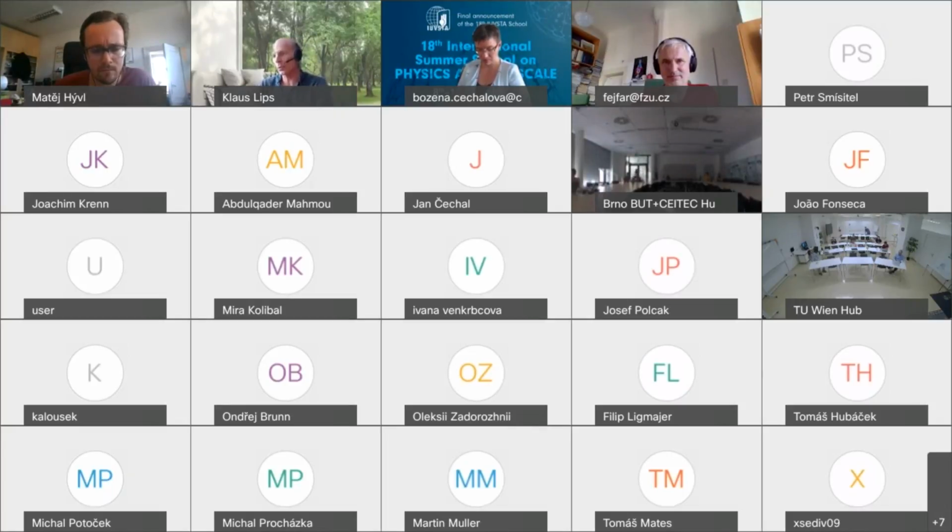For the holes, it has to be hole conductive. So you dope with phosphorus or with boron. That also takes time until you get that boron and that phosphorus in there. So you need a certain thickness to get that conductivity established. The thicker you make it, the better the conductivity will be, the more selective the contact will be. But the thicker you make it, the less light goes through, so you're blocking the contact again. So it is quite a complex interplay of getting everything together to get the maximum efficiency in your solar cell.